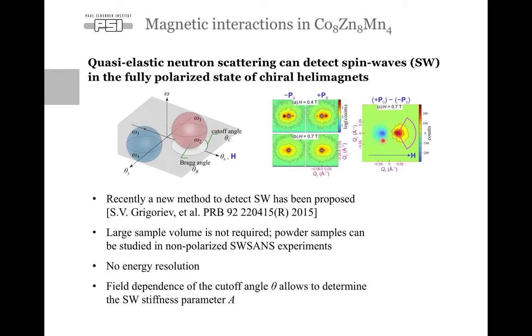It can be clearly seen that the non-reciprocal propagation of the spin waves in cubic chiral magnets can be very effectively probed with this polarized neutron scattering technique. And the advantage of this technique is that it has a much better k-space resolution than classical inelastic neutron scattering.